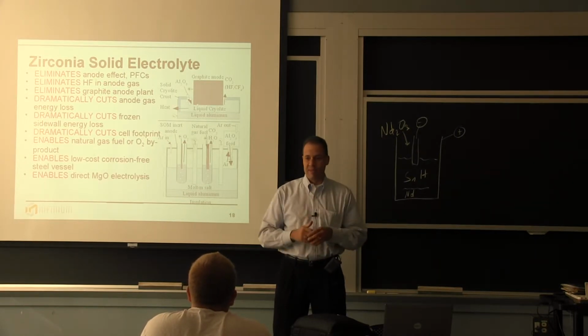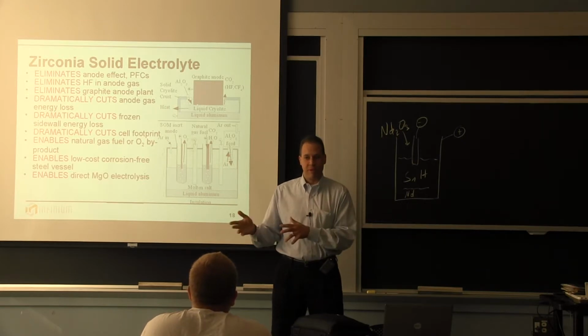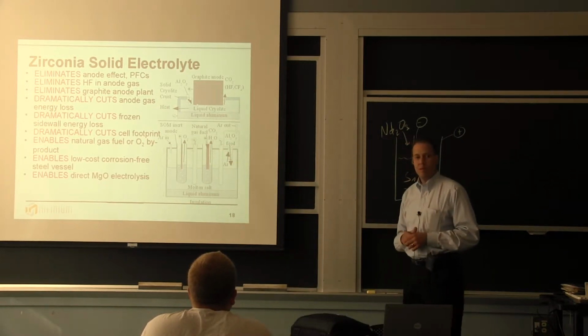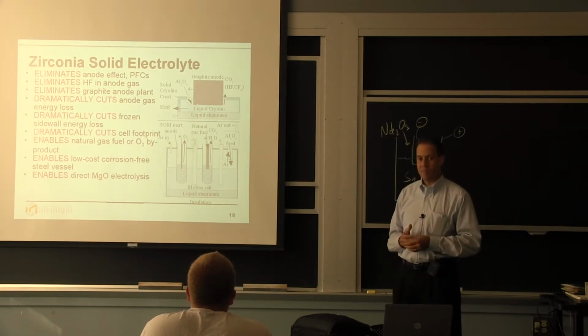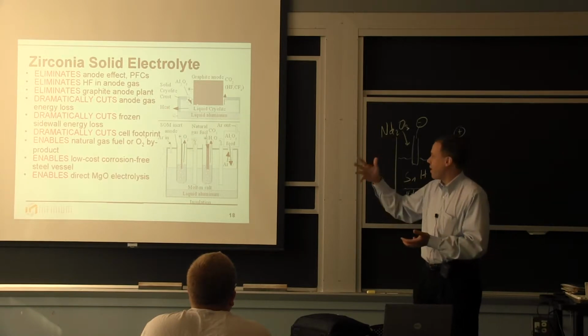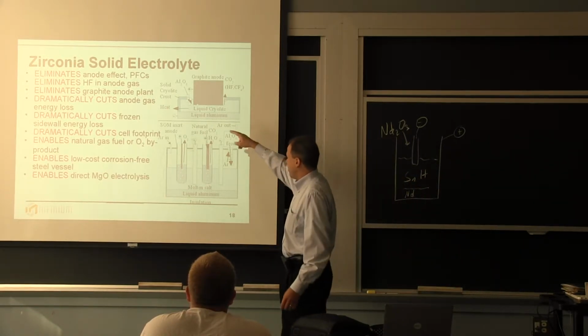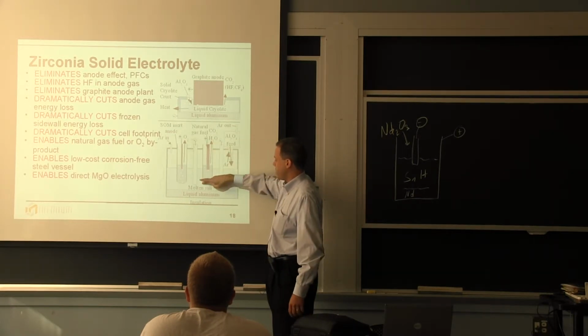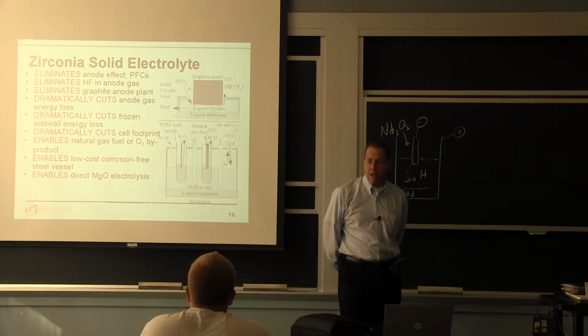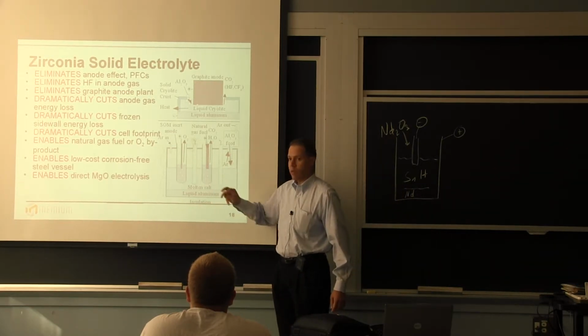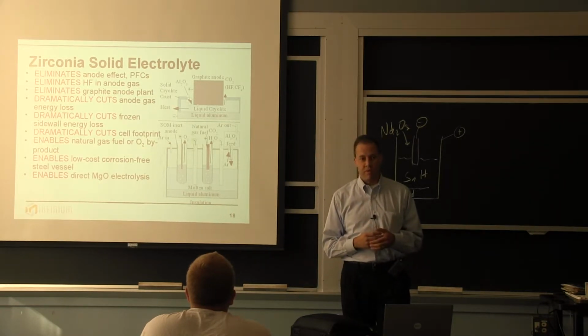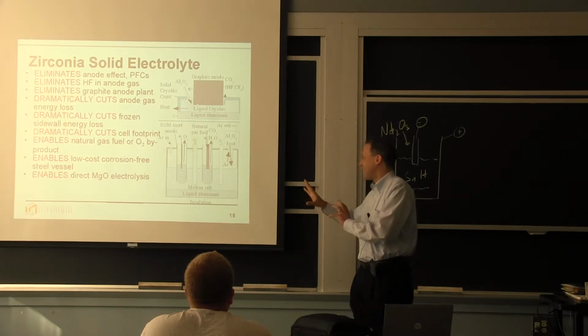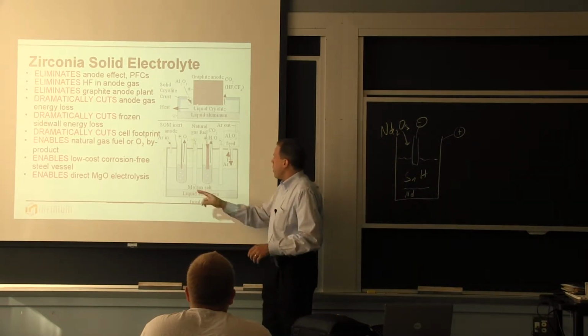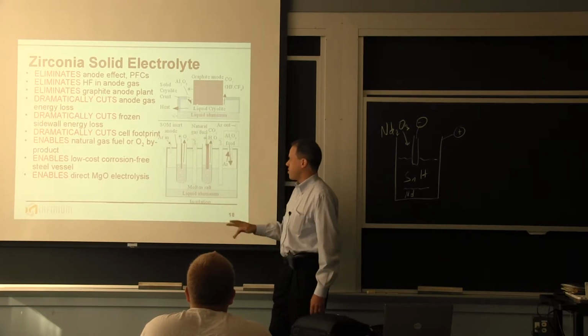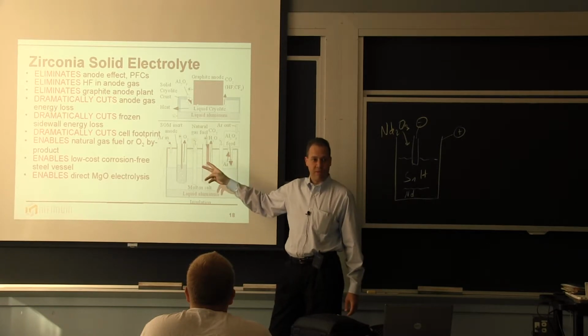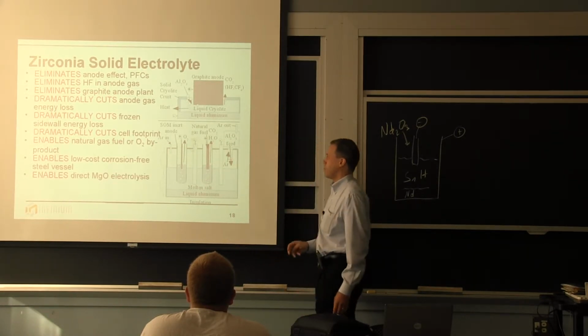So what comes off in terms of water and HF is about 10 to 1 to 20 to 1 water to HF ratio, but nonetheless, it's enough HF that you really cannot build a heat exchanger that can withstand the kind of acid corrosion. So in its place, we put a zirconium oxide solid oxygen ion conductor between the molten salts and the anode. We use a liquid metal anode. You can use the cathode materials of solid oxide fuel cells, porous perovskites, but it's very complicated. Liquid metals are very simple and robust. So you can use liquid silver to make pure oxygen, or you can pipe in natural gas to create a reducing environment, and then you make some CO2 and some water.